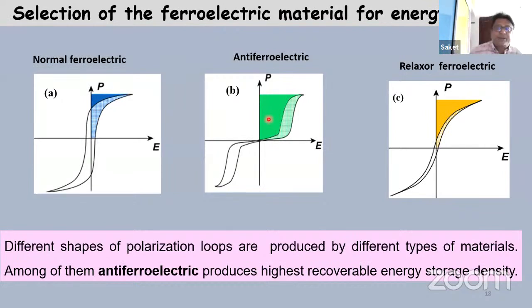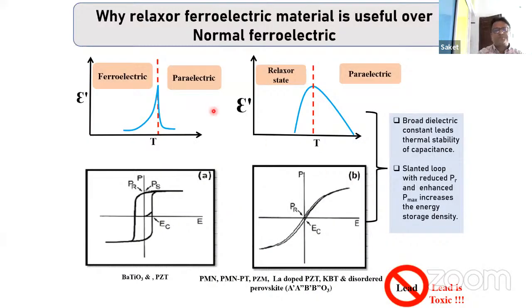But the thing is that most of these materials are lead based, and their breakdown strength is also not very good. So in that case, there is another material called the relaxor ferroelectric. Here, you can see that yellow portion, it is not like the green one, but still it is better than the normal ferroelectrics. And their loop is also very slim. So you are tackling the loss, reducing the PR, and breakdown is also better. So we are focusing more on the relaxor kind of ferroelectric. Maybe in the next slide.